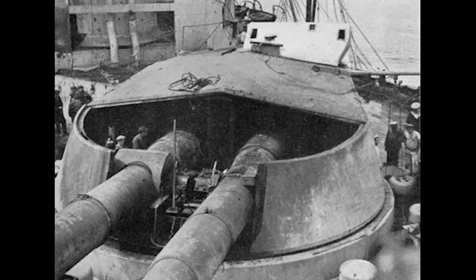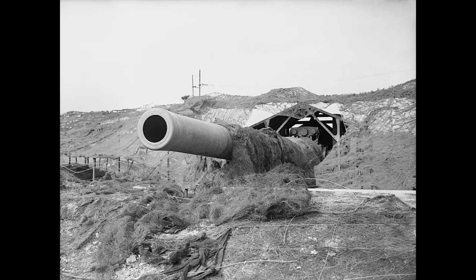German manufacturers followed a similar philosophy, though their projectiles were stronger than British designs and comparable in some respects to American projectiles. German KC new type armor, developed during the late 1920s and early 1930s as an improvement over the original Krupp cemented armor, featured face thickness of approximately 40 to 45%. This was thicker than British armor, but substantially thinner than American World War II armor. Surface hardness was maintained around 570 to 620 Brinell, providing good projectile resistance without excessive brittleness.